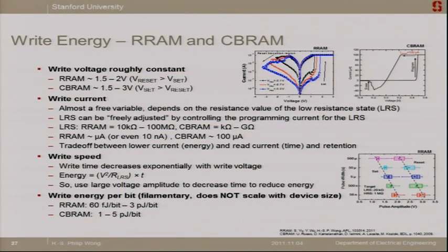Today, many of the RRAMs are operating at around a microamp of programming current. Some are even lower, like there are some papers that show 10 nanoamps of programming current. And the CBRAMs are operating at about tens of microamps or 100 microamps or so.